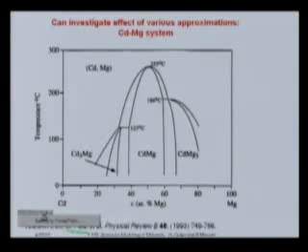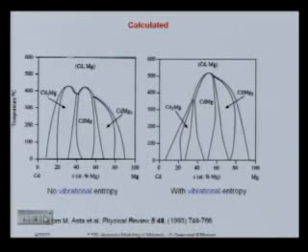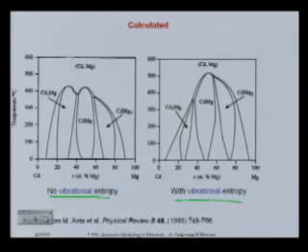So this is the experimental phase diagram, actually. So this is the calculation with no vibrational entropy and with vibrational entropy. So the first one is the one that I sort of showed you as the standard one. You just take the lowest energy for a lattice model configuration and you do Monte Carlo then with that. And this is if you literally do the whole phonon DOS for every configuration. And what you see is that there is some change in topology. I mean, look, this point has come down considerably and even has changed the topology somewhat. And usually that's what you'll see.